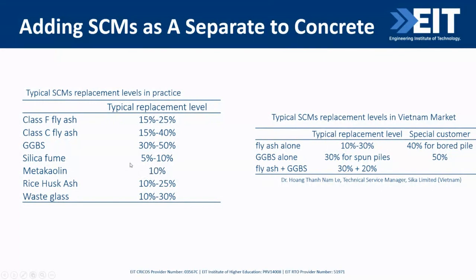Metakaolin is also used in applications where very low permeability or very high strength is required. So in such kind of applications, metakaolin is used more as an additive to the concrete rather than a replacement of cement. And the typical additions are around 10% of the cement mass. And then the performance of concrete using rice husk ash is dependent on many factors, including the level of Portland cement replacement, the particle size of rice husk ash, and so on.